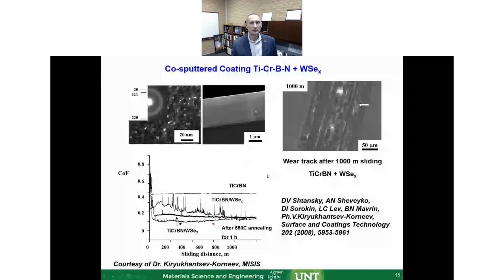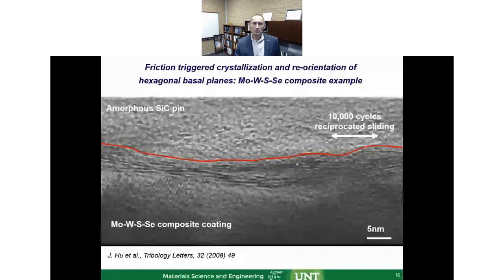This is from our results here, but I also have that confirmation from other research groups. This is the group of Dmitry Shtansky at the Moscow Steel and Alloys Institute. They are working on a titanium chromium boron nitride matrix with a tungsten diselenide addition, and similar results, you have a very low friction coefficient. When looking at the films here, you see the transfer film, and you can start forming this lubrication. When you look at a film in cross section, it looks fairly glassy. Perhaps some crystalline or nanocrystalline regions you can detect here, but mostly amorphous and very dense films, which will then develop the transfer film, which provides lubrication. All right, so let's look at the transfer film in much more zoomed view.